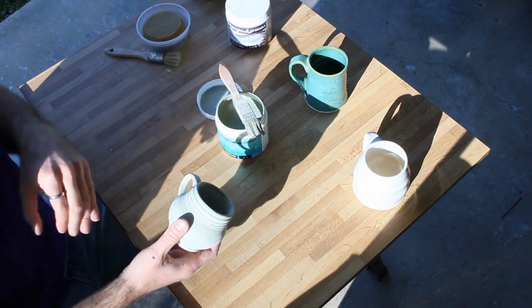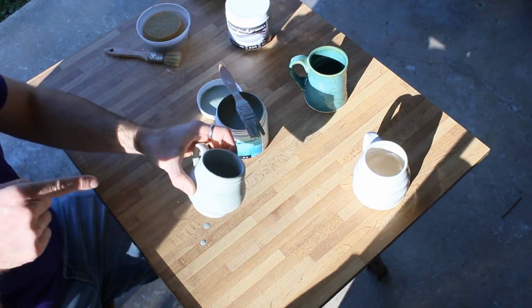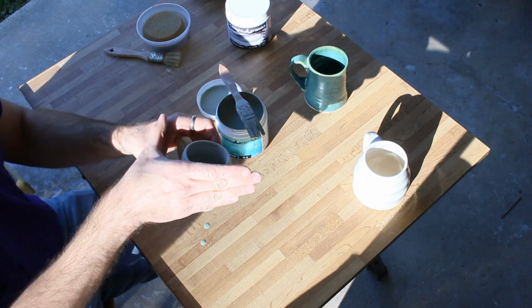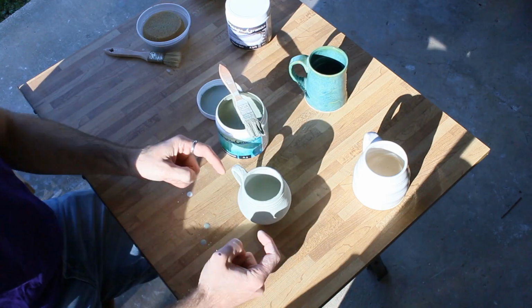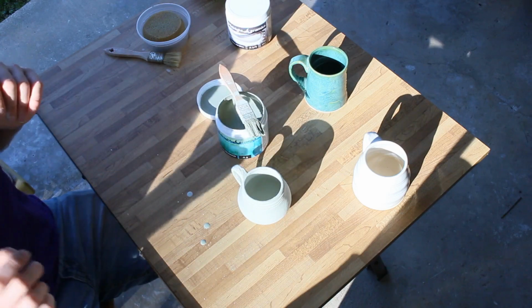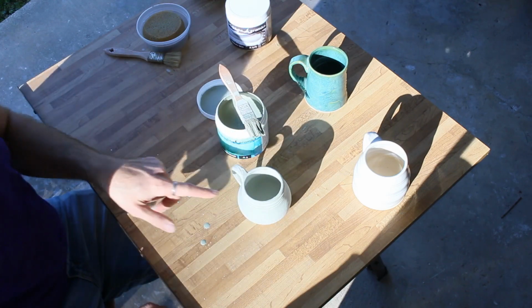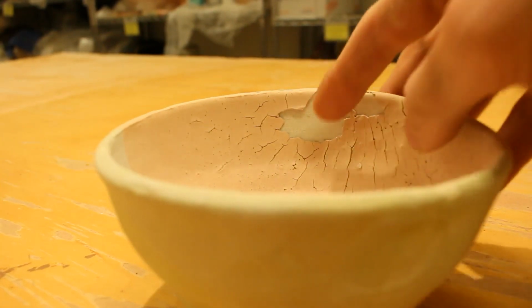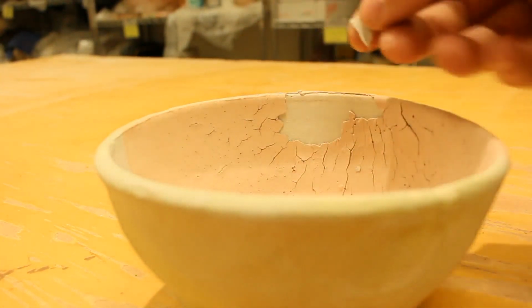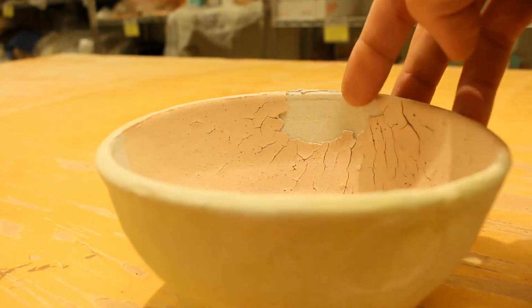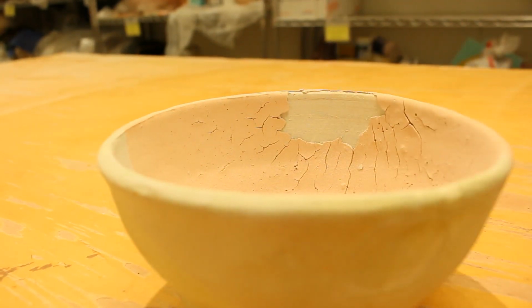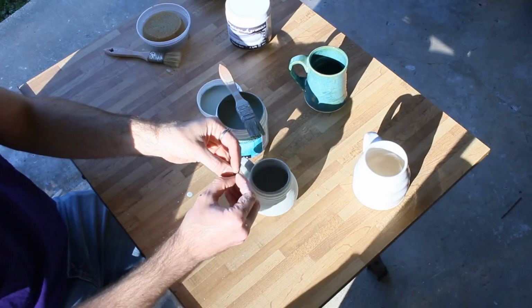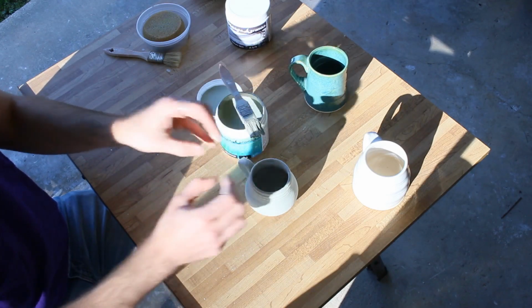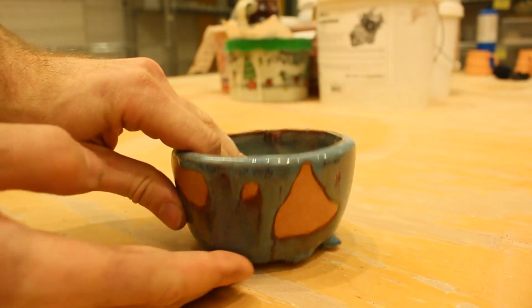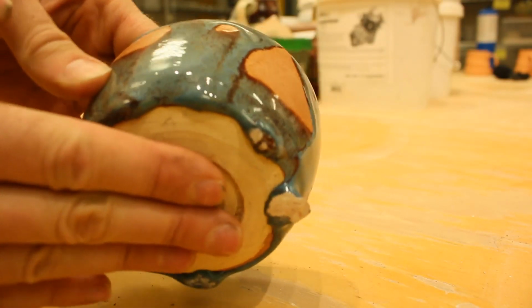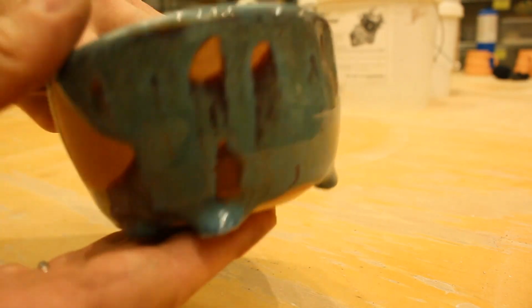And what can happen is as the glaze dries, instead of the glaze drying and shrinking and adhering to the pot rather than shrinking in, it'll shrink sideways because it's going to dry very, very slowly and water kind of has to evaporate from it slowly. And as it shrinks sideways, you might get these little cracks in the surface of your pot, right? And those little cracks that are in the surface of the glaze, when they go into the kiln and they start to kind of melt, they'll peel apart and you'll get these big bare sections of pot where there's no glaze whatsoever on that section of the pot. And that defect is called crawling, right?